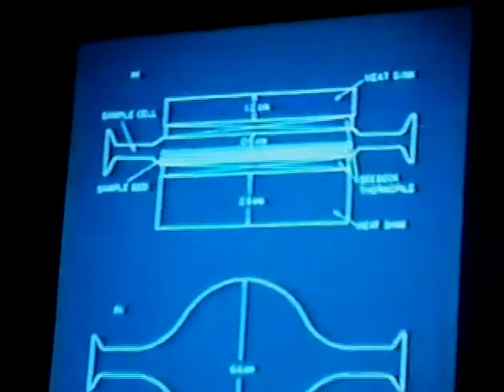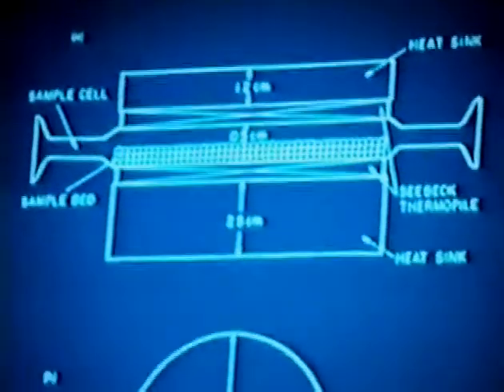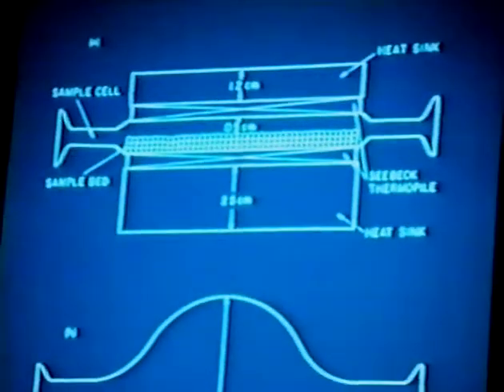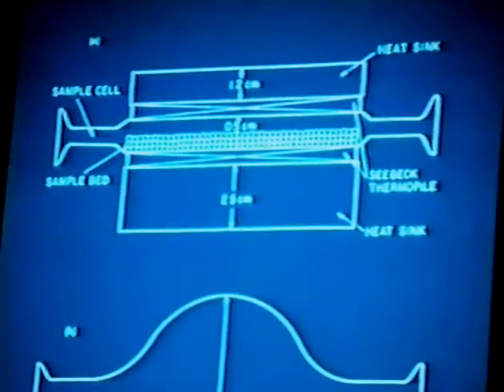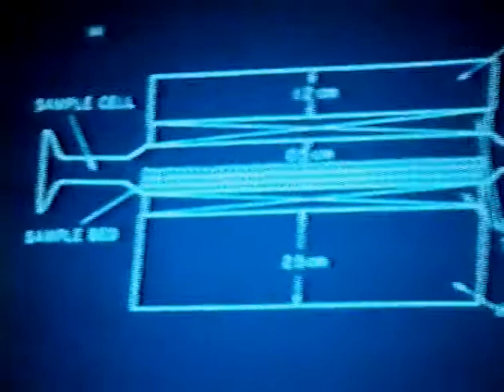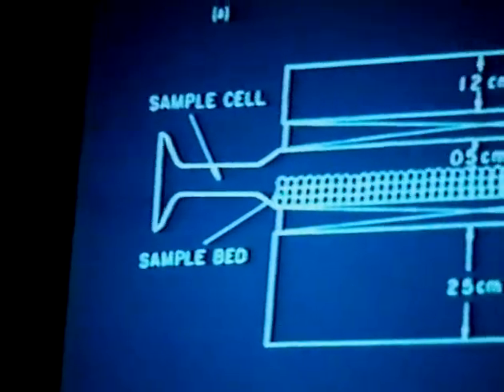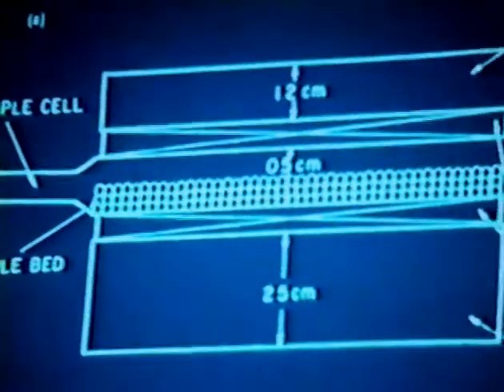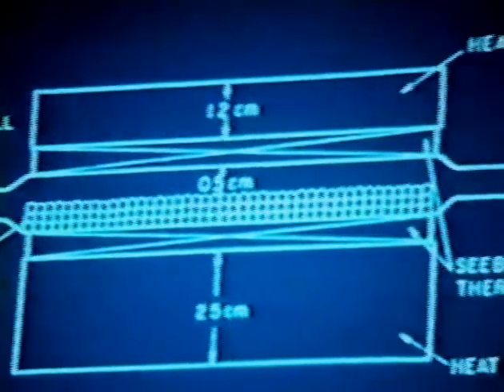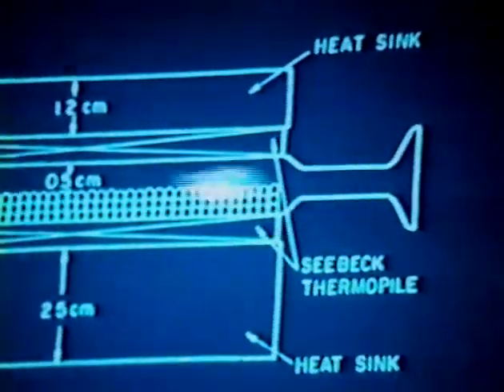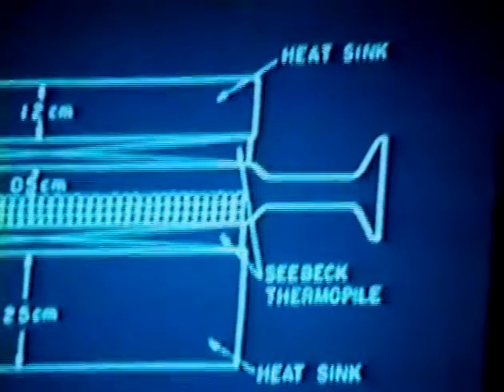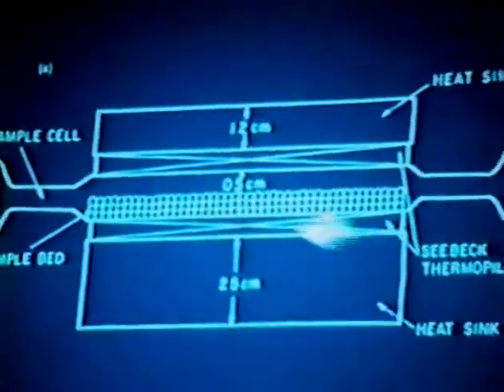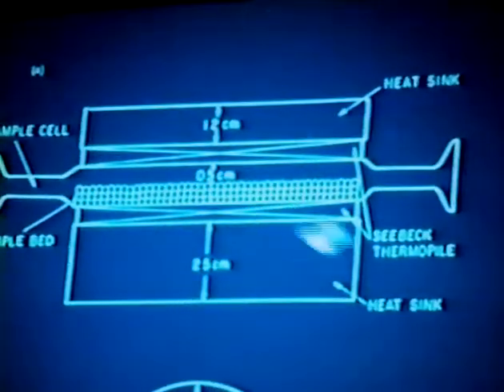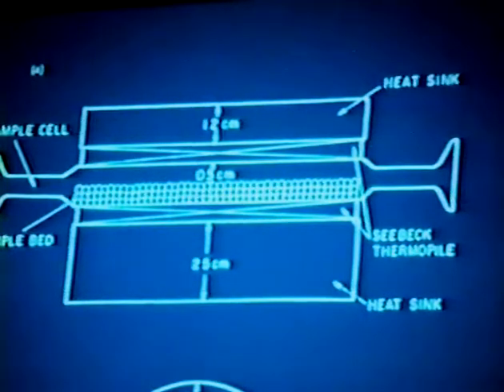What the calorimeter actually does is we run a typical chemisorption experiment and simultaneously measure the heat that's evolved as the gas is adsorbed on the catalyst sample. The cell is a flat, pancake-shaped glass system that's connected to the other volumetric pieces. The sample typically lies in a bed on one end of the calorimeter disc, and this disc is then surrounded on either side with thermopile sheets and then large aluminum blocks that act as our heat sink.